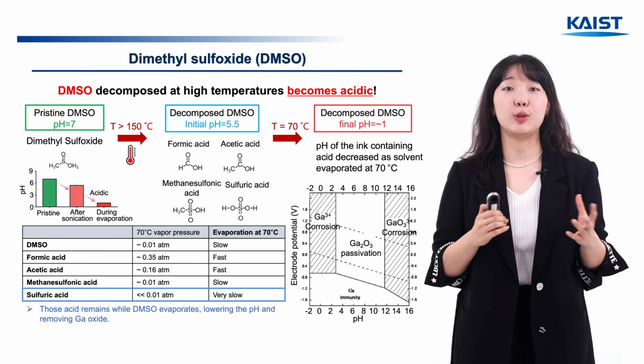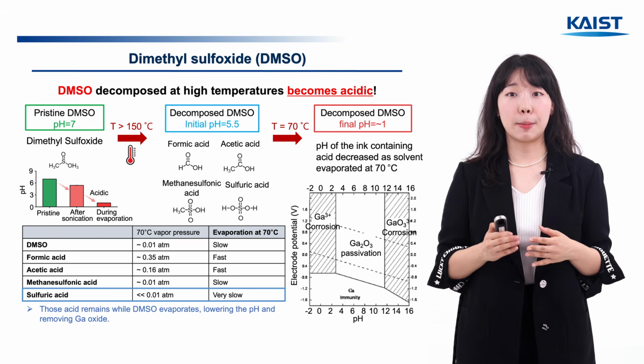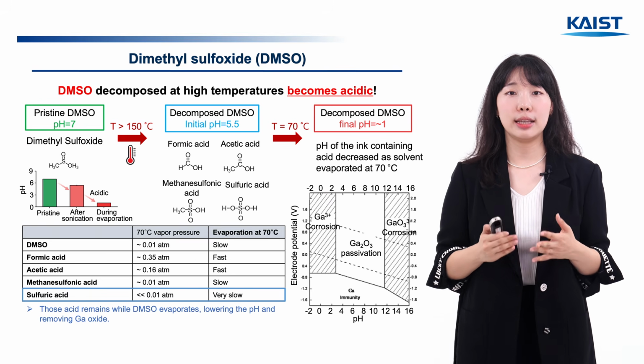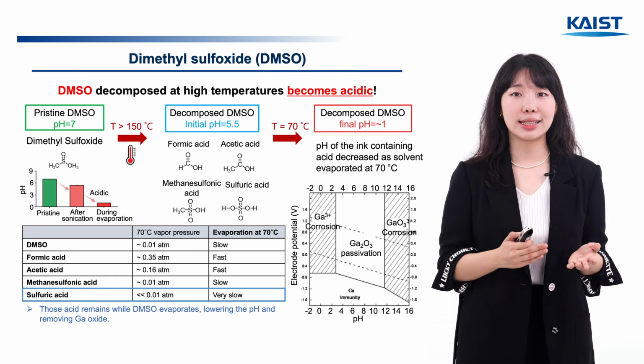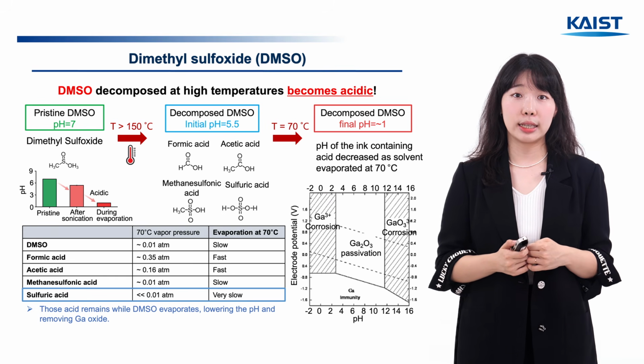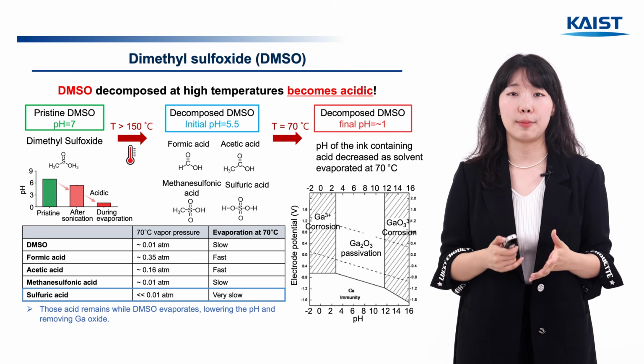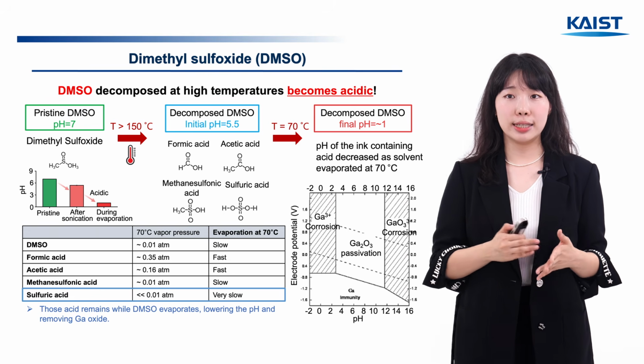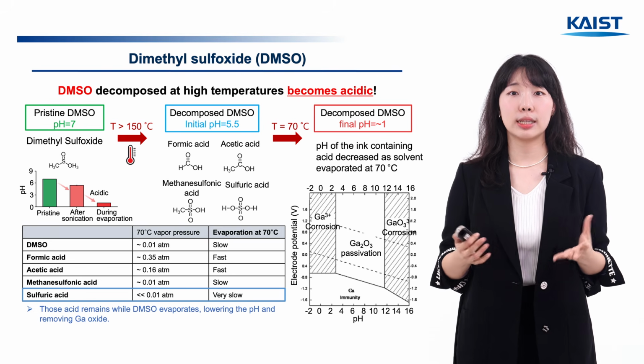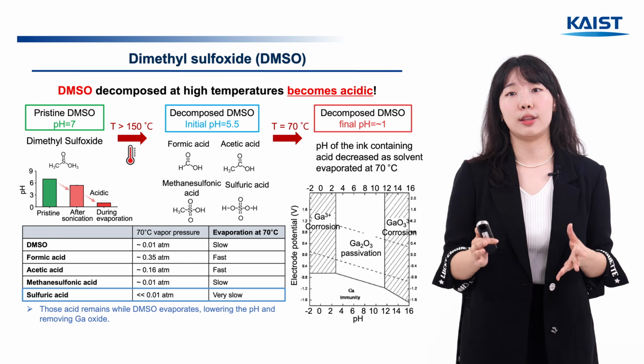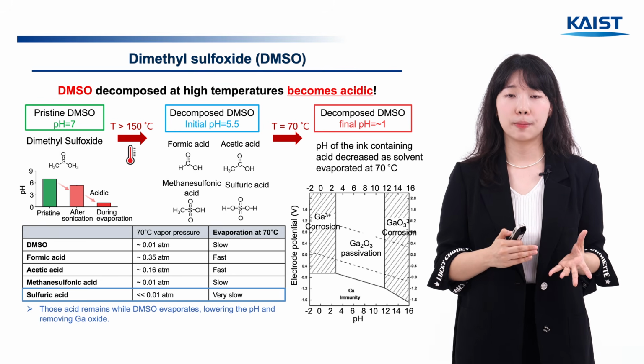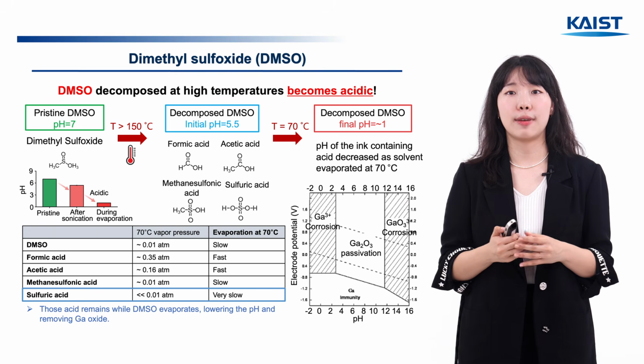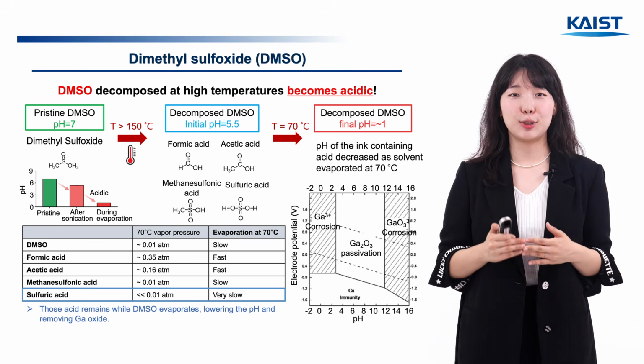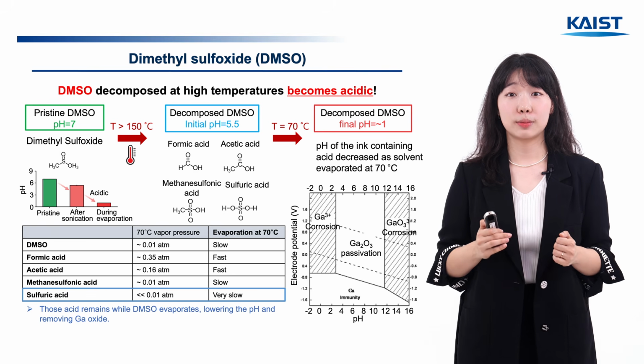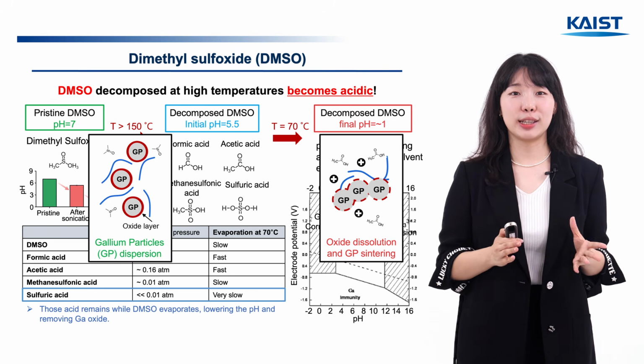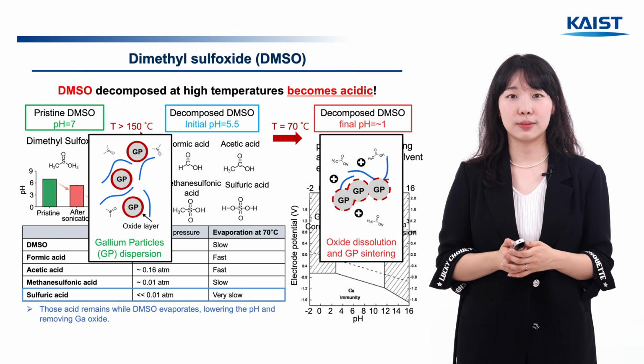DMSO starts out neutral. During tip sonication, the temperature rises to its boiling point, and it thermally decomposes and releases formic acid, acetic acid, methane sulfonic acid, and sulfuric acid, which drops the pH to 5.5. After that, when the printed ink is dried and the DMSO evaporates, the weak acids evaporate along with the DMSO because of their low boiling points. But strong acidic compounds evaporate slower, so they stay behind, gradually lowering the pH down to about 1. So the initially dispersed gallium particles can be sintered together at acidic condition.